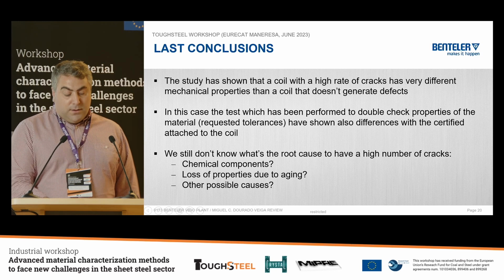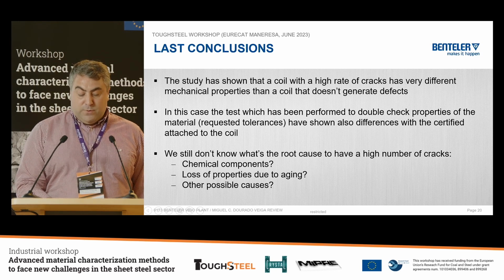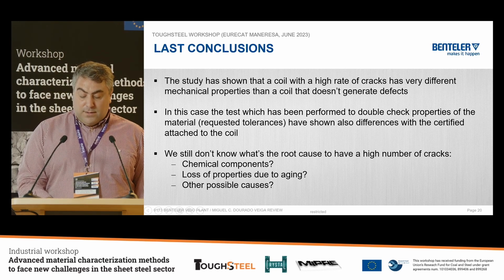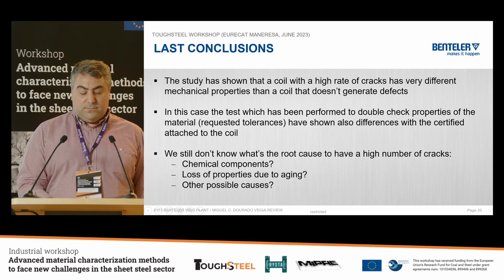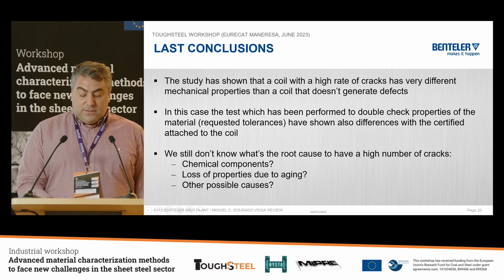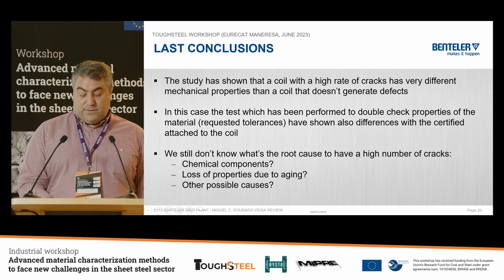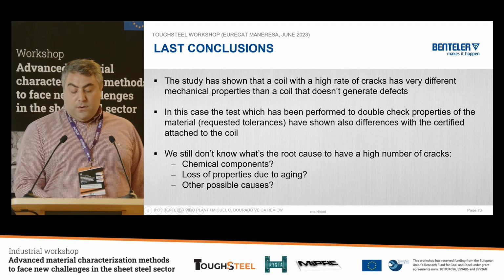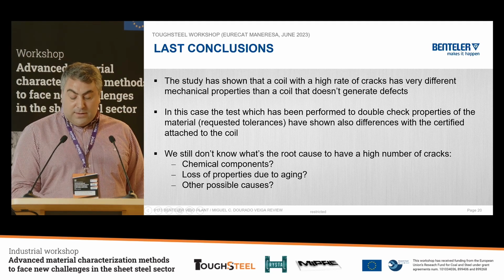Conclusions. The study has shown that a coil with a high rate of cracks has very different mechanical properties than a coil that doesn't generate defects. In this case, the test which has been performed to double-check properties of the material requested tolerance has shown also difference with the certificate attached to the coil.